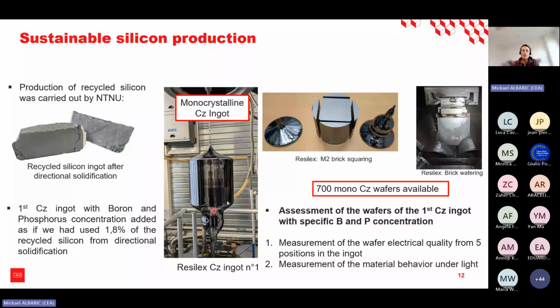So it's a small one, a 30 kilogram CZ ingot, but it was perfectly adapted. You can see this ingot has been squared into a brick compatible with the M2 size wafers. The brick has been ground, and after the grinding step, we cut the brick into wafers. So from this ingot, we were able to produce more or less 700 mono-CZ wafers.